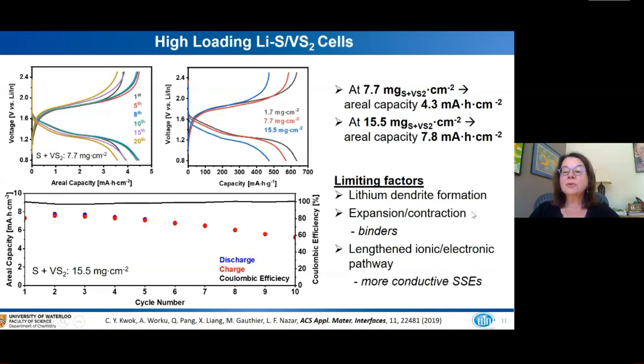We're also able to create or fabricate fairly high loading cells that are shown here. This is the data for 7.7 milligrams per square centimeter, all the way up to 15.5. And of course, this started when we really increased loading of the cell. This is of the sulfur and the VS2.